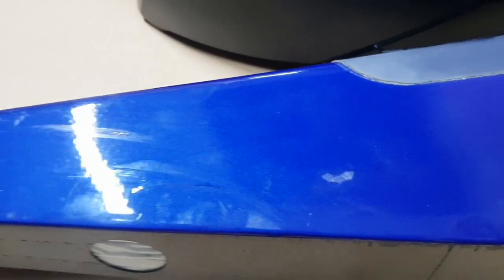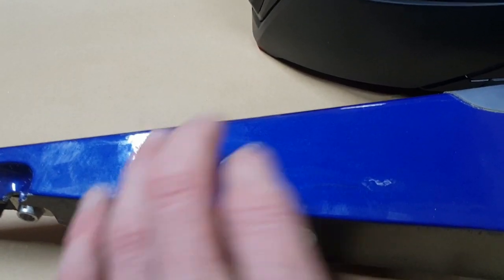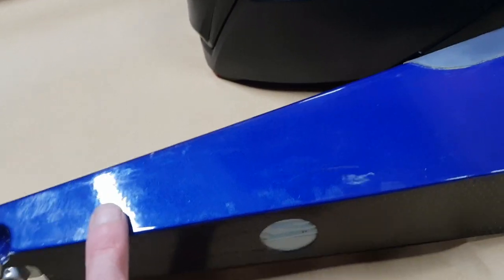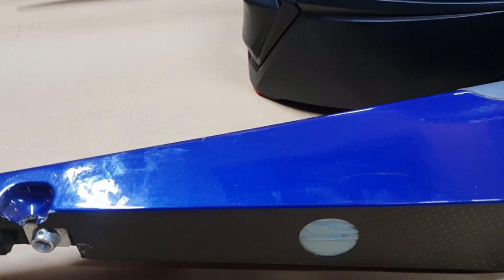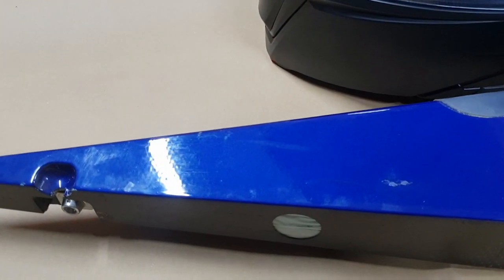It was a big problem with the early F40s, because the engineers applied the paint as thin as possible, because they wanted it as light as possible. And when the F40s then came out of Italy and went into dealers in mainly, I think, the UK, a few in America as well, a lot of the customers were complaining that after spending all this money, they could see the carbon fiber weave through the paint. So would you believe it, a lot of the F40s were painted by the main dealers after coming out of the factory. They were all flattened, primed again, and painted, just because they got a good few complaints.